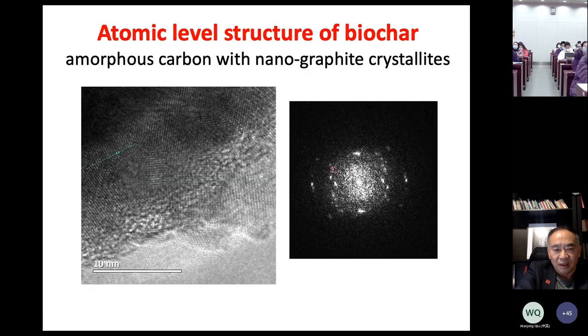And also if we look at the nanostructures, for crystal structures, these are TEM pictures of biochar produced from maple. What we can see here is some crystal structures, and based on the diffraction patterns, we know that those crystals are graphite nanocrystals. Okay, so what we can see here is that biochar itself is porous because it retains the structure of wood, and at the same time the carbon itself is amorphous carbon with embedded nano graphite crystals.